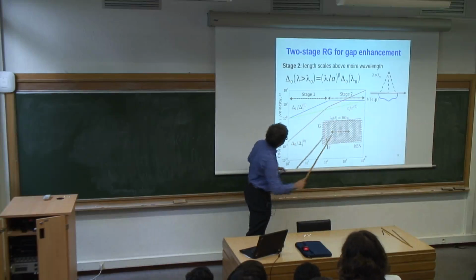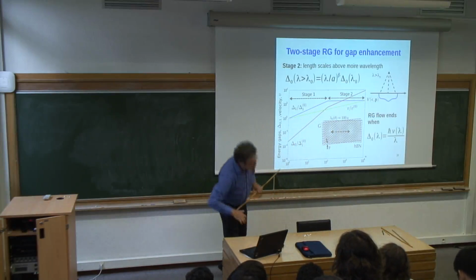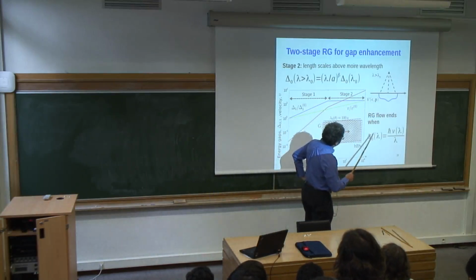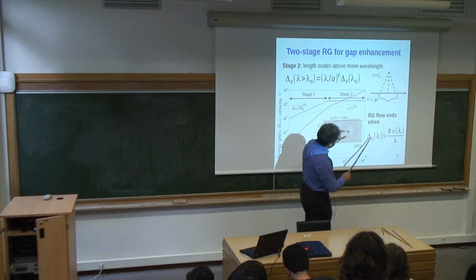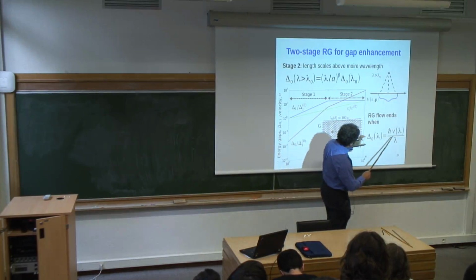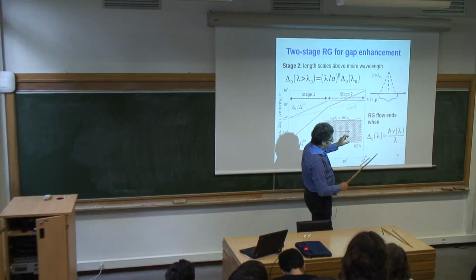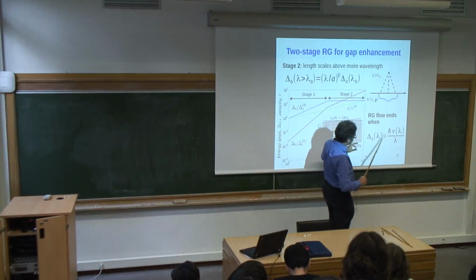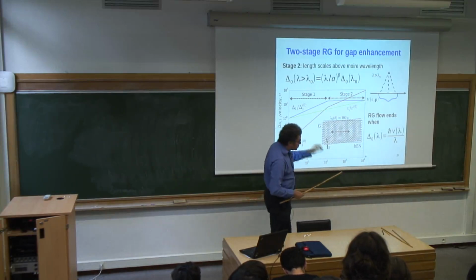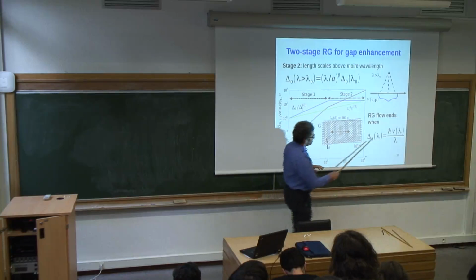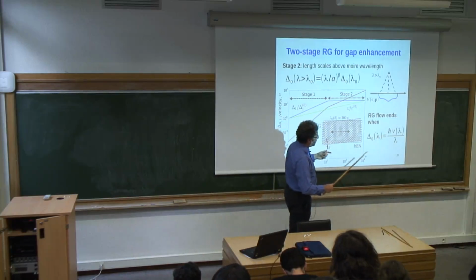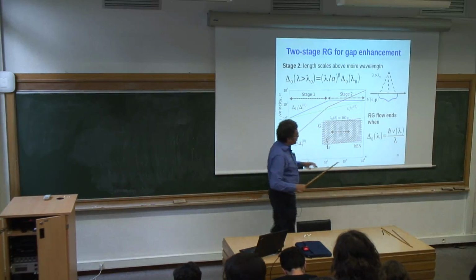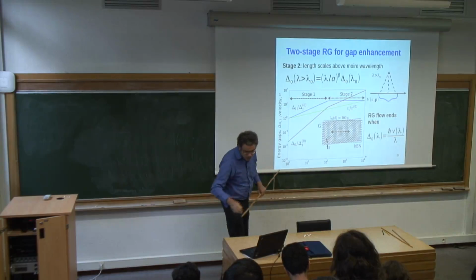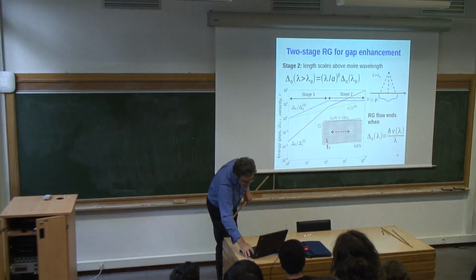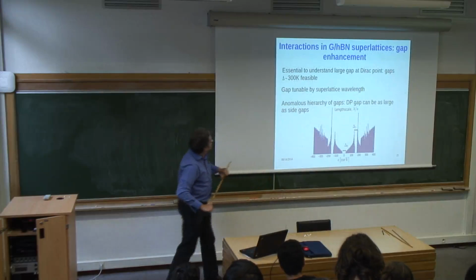It first grows rapidly, then grows less rapidly, and then it terminates when you reach the length scale at which the gap growing as a function of length scale reaches the particle kinetic energy that you computed without accounting for the gap. So there is a self-consistent condition for where you terminate the renormalization group, and that determines the length scale and therefore the gap size that you predict from this analysis. And so that's where these numbers come from. Okay, so I think that's the end of what we discussed yesterday.